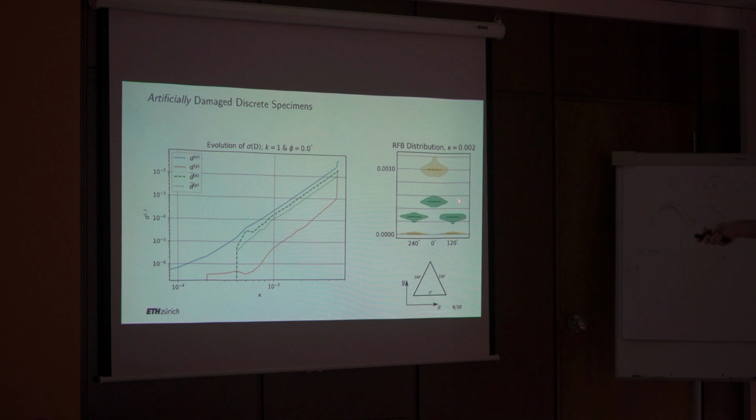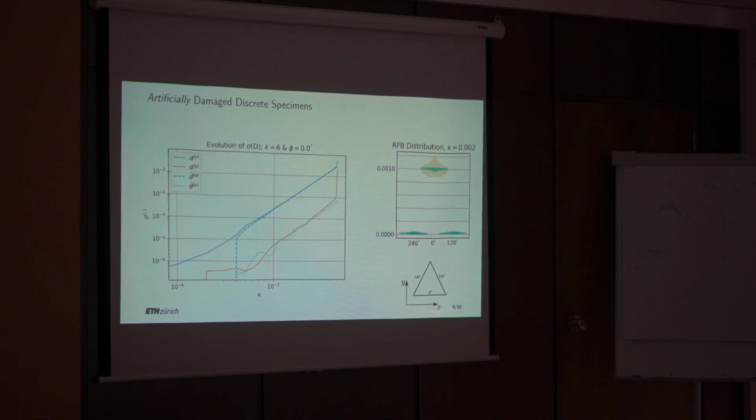And here you see the reason. We see that while the number of beams that have been selected is correct, we selected the wrong beams. You see, we have not selected enough horizontal beams, but we have selected way too many inclined beams. And so when we increase k, also meaning making the directional component more important, then you see that it gets better, until at around 6 we get satisfactory results.